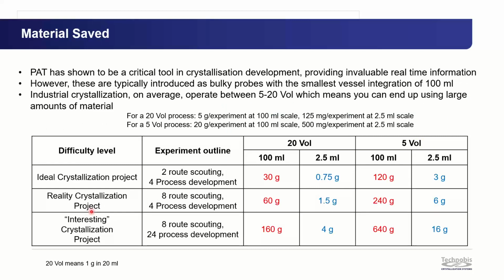And another big benefit of being able to introduce PAT at a low scale is the reduced amount of material you can save. So PAT has been shown to be a critical tool in crystallization development. It's used in practically every example of crystallization development for producing invaluable real-time information. However, these are typically introduced as bulky probes, and the smallest vessel that these typically are used with is 100 milliliters. So I did some calculations based on some experience I had, knowing that typically processes are between 5 to 20 volumes, and a volume is defined as 1 gram to 20 milliliters. So for a 20 volume process, 5 grams per experiment at 100 milliliters, or for 5 volumes, 20 grams per experiment.